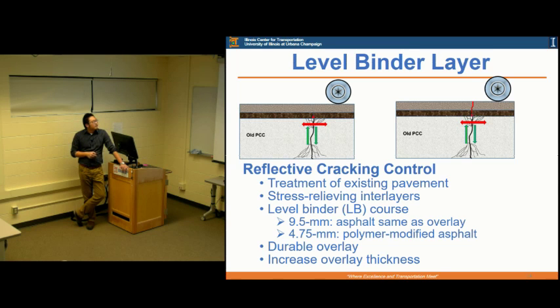There's a lot of methods you can use to control that reflective cracking. For example, you can do some treatment on the existing pavement. You can also put an interlayer trying to release the stress, and also you can put a level binder course. That's what we are doing right now. There's two kinds: one is the 9.5 millimeter nominal aggregate size, and also you can use the 4.75. Also, you can improve your overlay mixes, use more durable and much better quality, and also you can increase the overlay thickness. If you get a very high thickness, then the reflective cracking is going to be less. That's the way we control our reflective cracking.